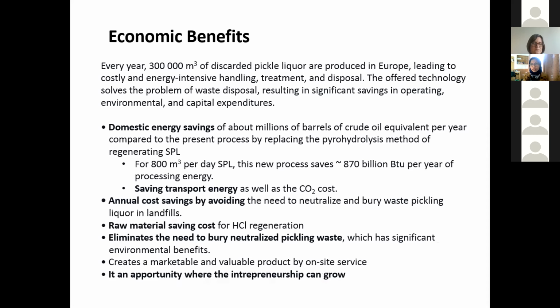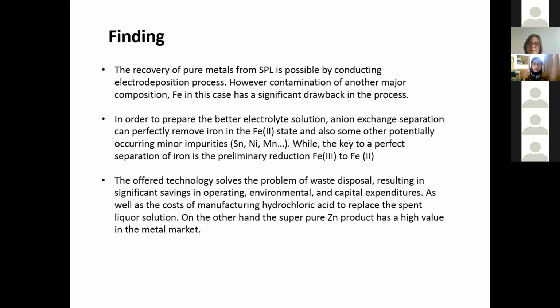And the raw material, hydrochloric acid, can be sent back to the pickling bath, and it makes an opportunity where entrepreneurship can grow. And the finding is that the recovery of pure metal from the SPL is possible by conducting the electrodeposition process, and it will be better if we do the separation process before, which we can do with the anion exchange process. And yes, it will solve problems like waste disposal, resulting in significant savings in operating, environmental, and capital expenditure. And also we have a high value product, which is high purity zinc.